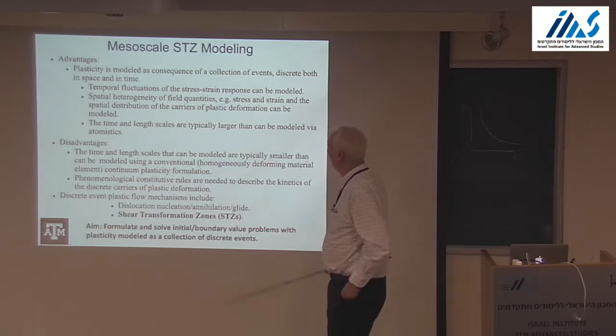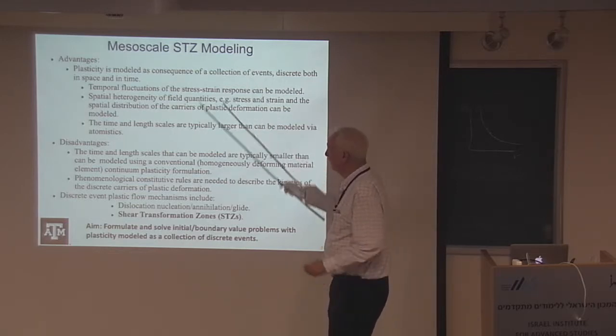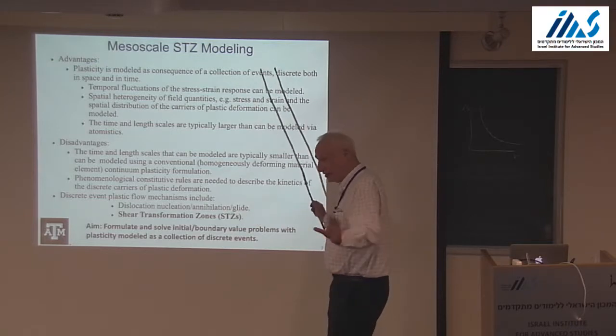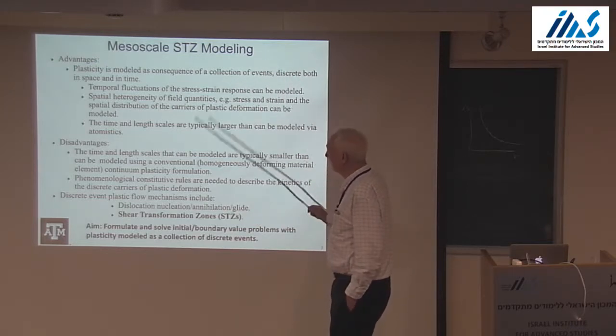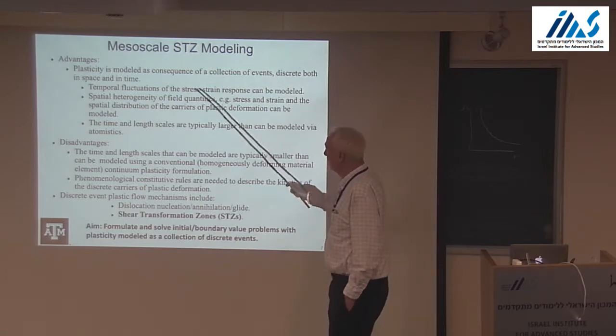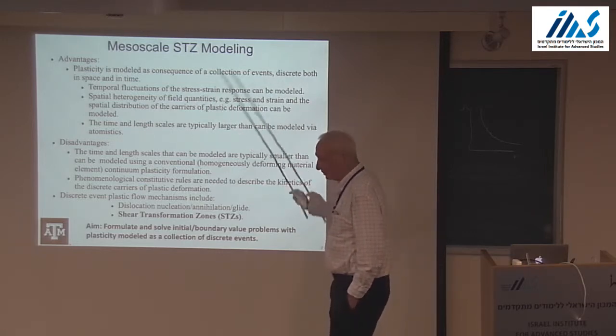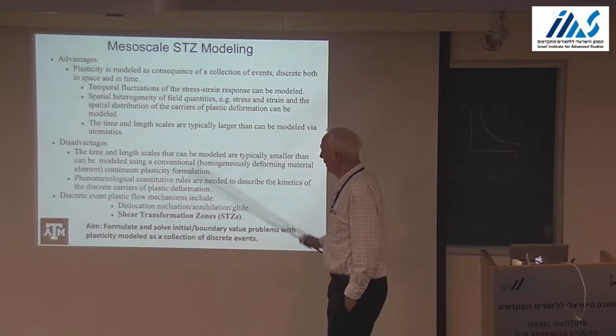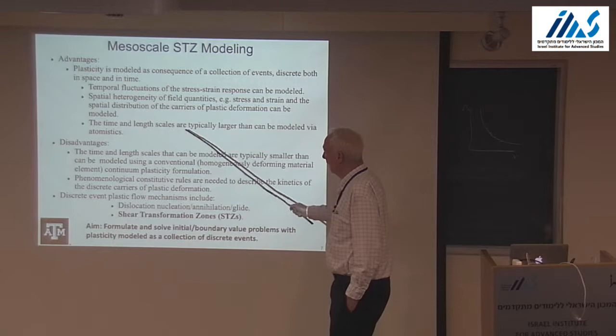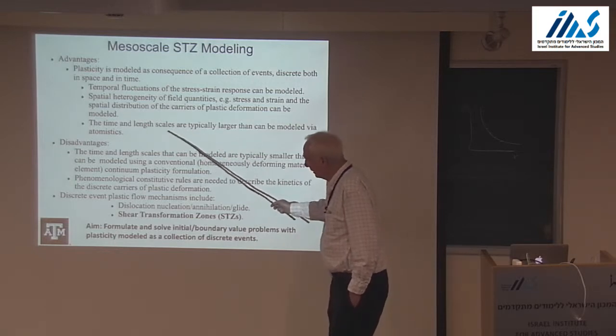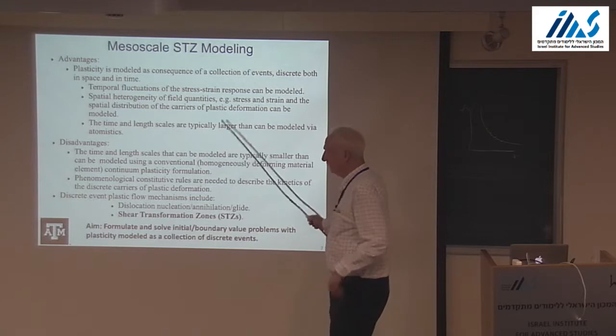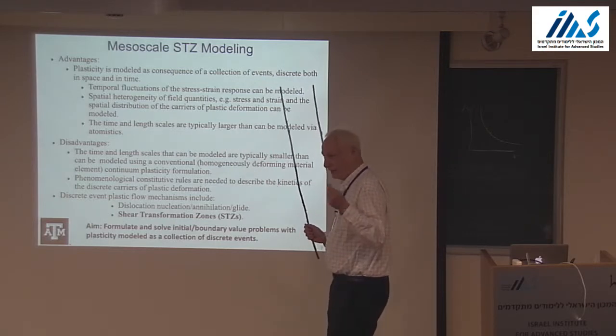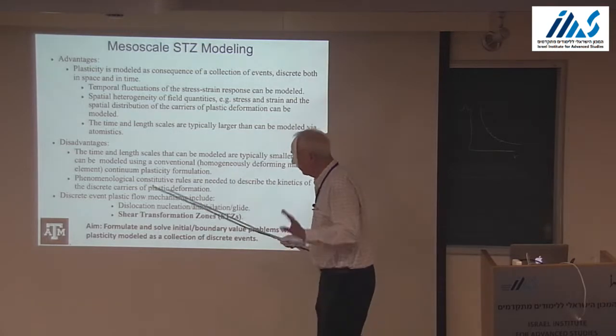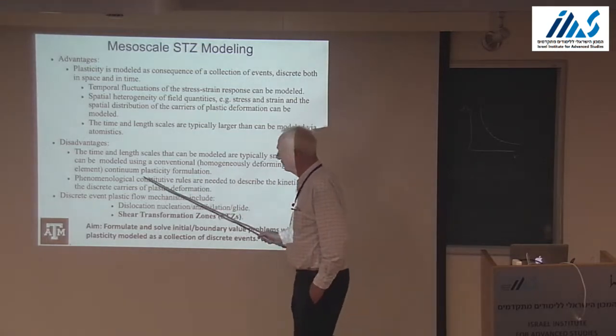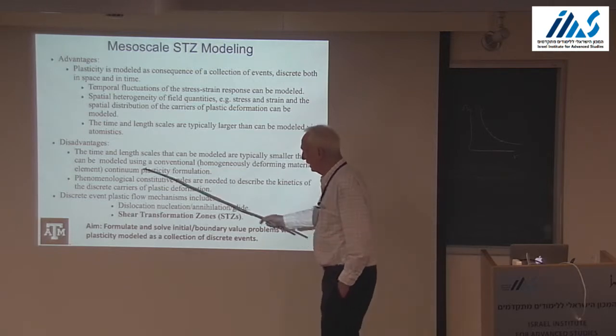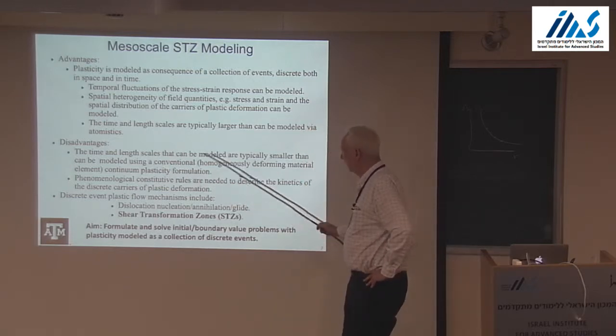Okay, so at this scale I'm going to model plasticity not as a continuum framework, but as a collection of events that are discrete in space and time. This enables these temporal fluctuations and the spatial heterogeneity to be modeled. The length and time scales seen in experiments are typically larger than what you can model by atomistics. So we can get to large. Although here we're still going to do very, very small size scales, but our time scales are going to be longer.